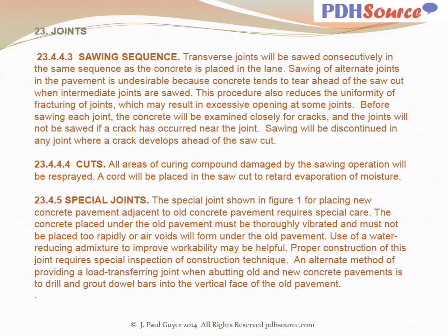The special joint shown in figure 1 following, for placing new concrete pavement adjacent to old concrete pavement, requires special care. The concrete placed under the old pavement must be thoroughly vibrated and must not be placed too rapidly, or air voids will form under the old concrete pavement. Use of a water reducing admixture to improve workability may be helpful. Proper construction of this joint requires special inspection of construction technique. An alternate method of providing a load transferring joint when abutting old and new concrete pavements is to drill and grout dowel bars into the vertical face of the old pavement.